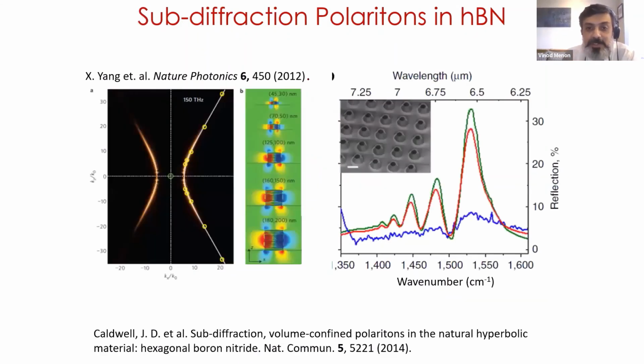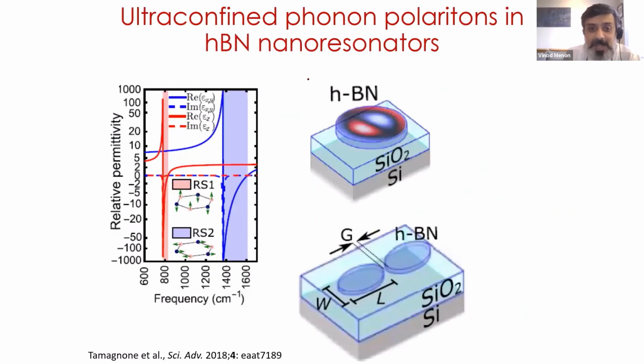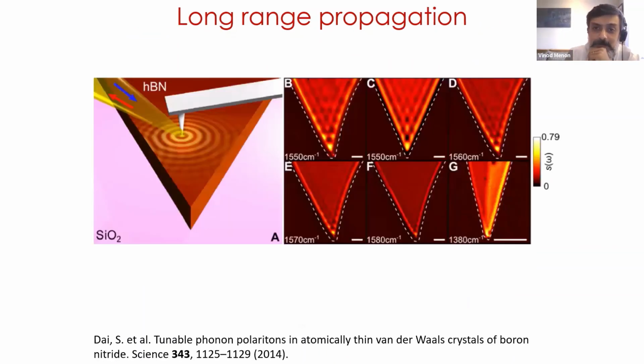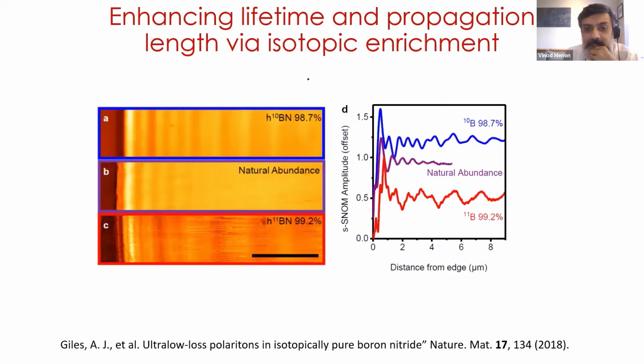And the nice thing about them is you can now make all sorts of interesting properties, like making cavities that are sub-wavelength. And in fact, they've shown this. You can make a boron nitride cavity that is sub-wavelength because you are not limited by the largest wave vector that you can excite in these systems, and you can get propagation of phonon polaritons over long distances. And you can see here that you can propagate up to 8 to 10 microns in these systems. Again, the key here is that these are all in the mid-infrared part of the spectrum.